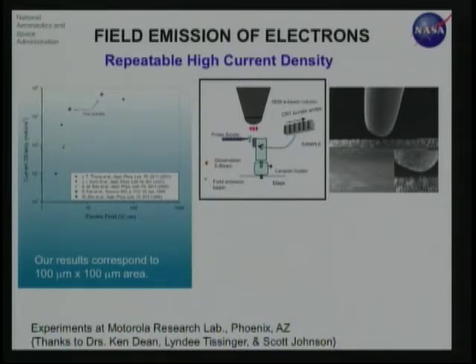So they have a scanning electron microscope where you put the sample in, and then your observation beam is coming down onto the sample, as shown here. Here this shows you the nanotubes which are perpendicular to that axis, and the microprobe anode which just runs through.